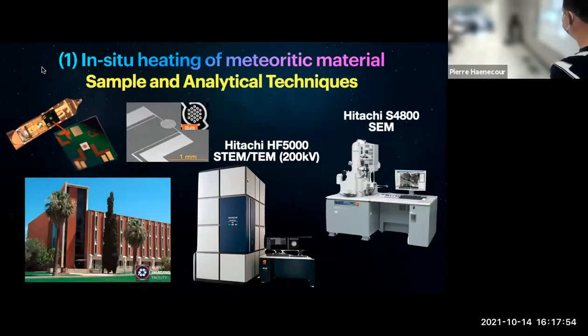And then more recently, just in the past few months, we also acquired a new heating system for the Hitachi S4800 that we have in the facility here. So in addition to doing heating with a 200 kV TEM, we can also do it at 30 kV on an SEM instrument.